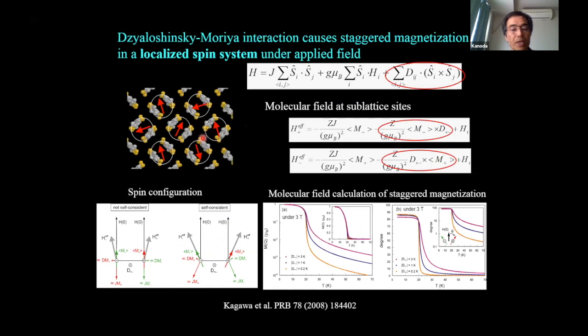And this is the in-plane structure again. The spins are sitting on the dimer here, and on the neighboring dimer, other spins are sitting here. So these adjacent spins have no inversion symmetry. In such a case, the Dzyaloshinskii-Moriya interaction works, even if it is very small in organic materials, but it is there. So in this case, even in the paramagnetic state, the application of the uniform magnetic field generates a staggered effective field. A simple consideration explains this situation.